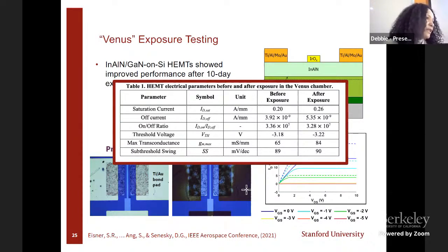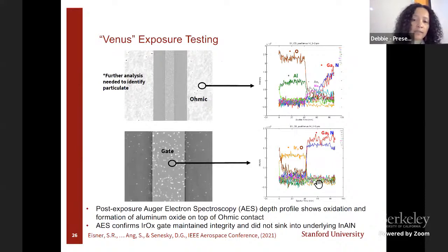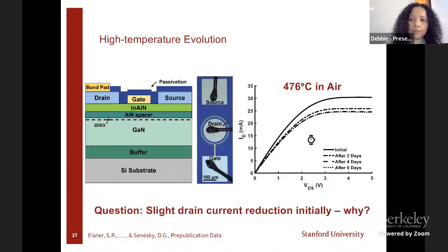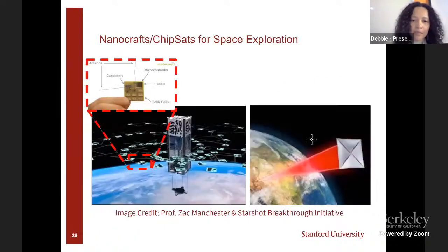Diffusion, right? So creating a eutectic, depending on the metal, sometimes this evaporates. Iridium oxide doesn't sink. We're showing it's actually staying on top based on our Auger electron spectroscopy. So you do want to create a eutectic, but you want it to be Schottky in nature and also stable as well. So more data.